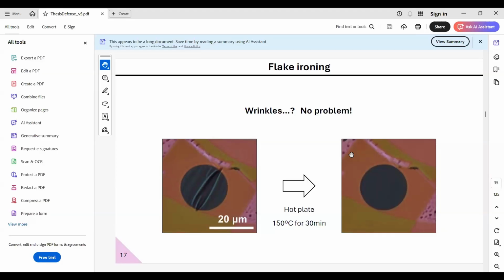So if you press them against the hole, they will obviously like to stick to the sides of the hole. And I think just because of this, we have much flatter, much nicer regions, as we can show here. Maybe here, the conformation on the gold was not so good, and when we heat it up, it accommodates and produces a flat region.